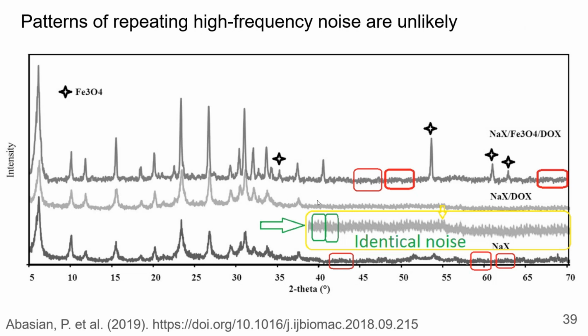And then we have a much more egregious thing here where there were probably some peaks that they wanted to remove from this part of the spectrum. So they just took a little blurb of noise and just repeated it 100 times in a row. And that is never, ever going to happen in a legitimate X-ray diffraction pattern.